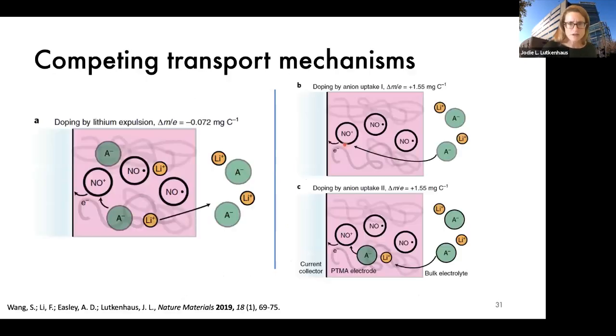But after some thinking, we were able to consider that maybe the mode of mass transport or ion transport isn't as simplistic as I thought it was. So what I was introducing to you originally was this idea that there's some electrolyte out here, and when one of these sites becomes oxidized, an anion comes and diffuses in and dopes the polymer, and we're all happy. But the picture is now revealed to be much more complex than that. The polymer is actually swollen with solvent and electrolyte. So the real case is the polymer already has some salt in it naturally.